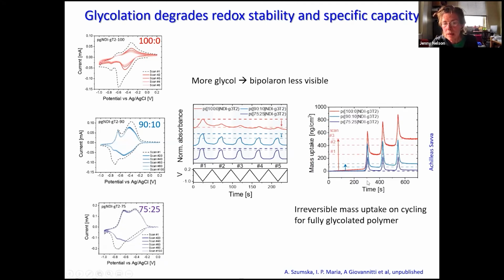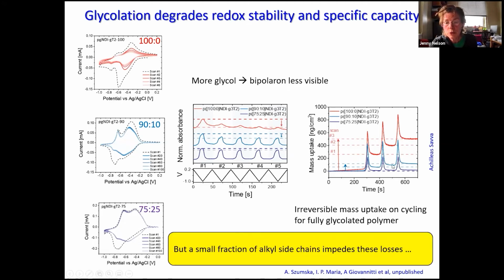We've also looked at the mass uptake under electrochemical charging by the polymers, and we find that in the case of the fully glycolated polymer, there is a mass uptake which is somewhat irreversible from cycle to cycle, whereas in the case of the partly alkylated polymer, that effect is reduced. So it seems as though full glycolation is not advisable, doesn't lead to good performance for this polymer, but introducing a small fraction of alkyl side chains helps to impede these losses. Before going on, I want to make one point, which is that all of this work is done in degassed electrolyte.